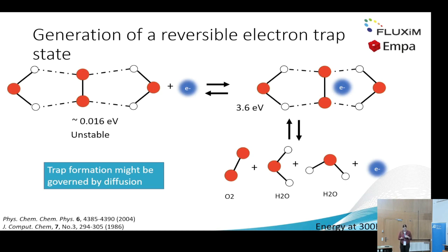Now, another question that is important is to see we have electron traps which develop slowly over time. And it takes longer than we usually would expect for electron traps to be filled. And the question is, why is it that much longer? So we are talking about a difference between 200 microseconds to about 1 second to 15 minutes.